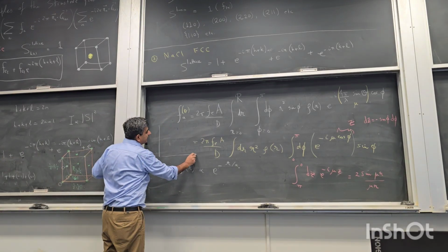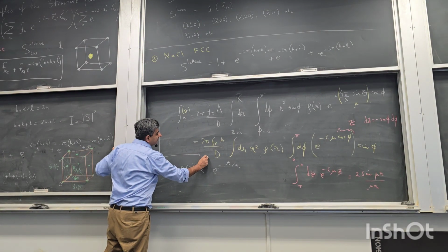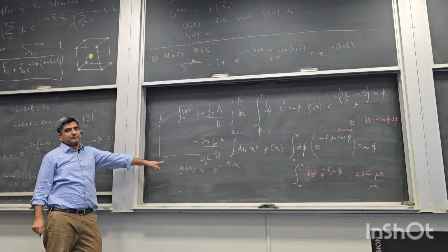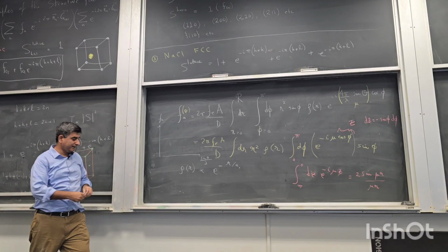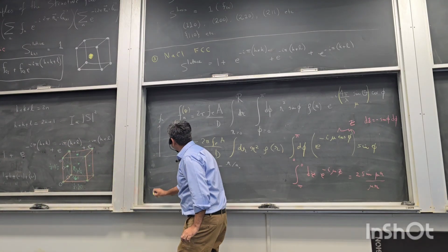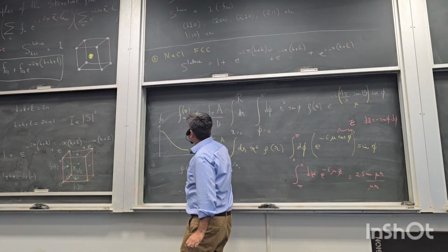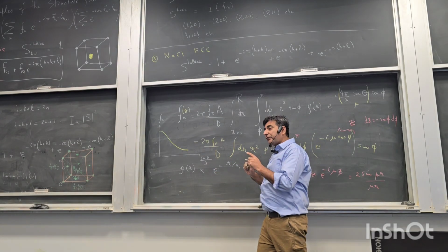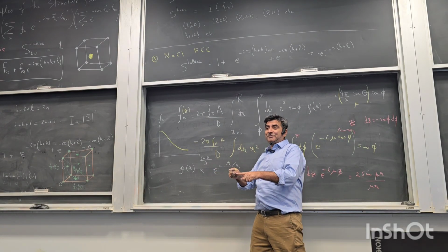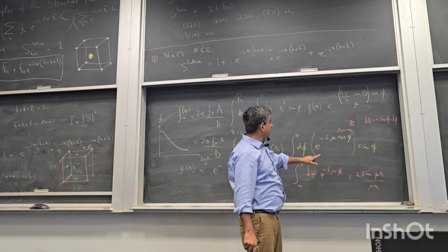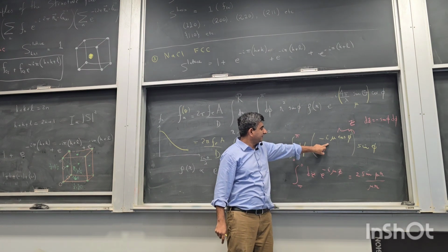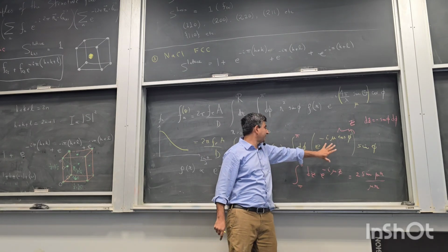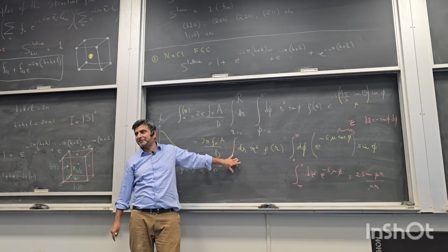Generally, there are tables available that plot f a versus mu or sine theta, and generally these tables and graphs look like this. For large thetas, these FAs go down, and for theta equals 0, this thing becomes 1, this becomes independent of theta, and you're left with this integral.